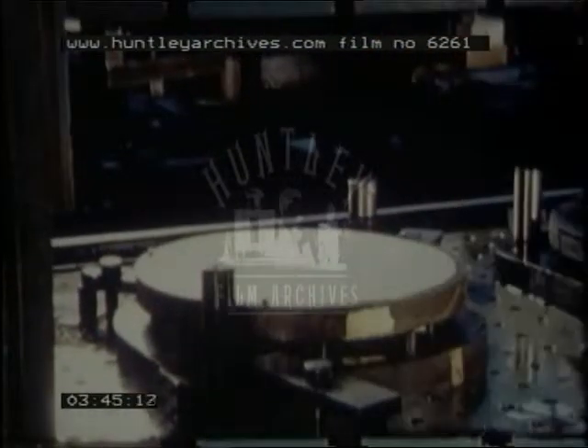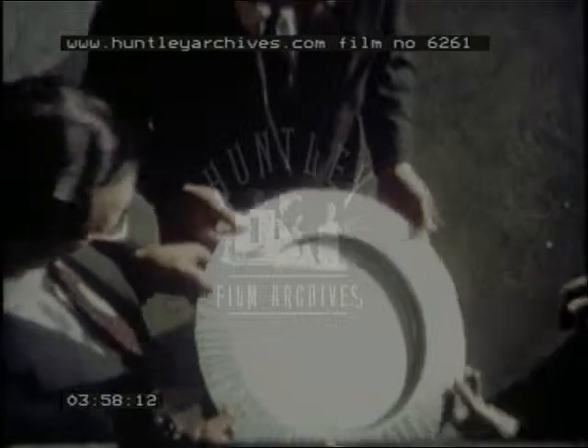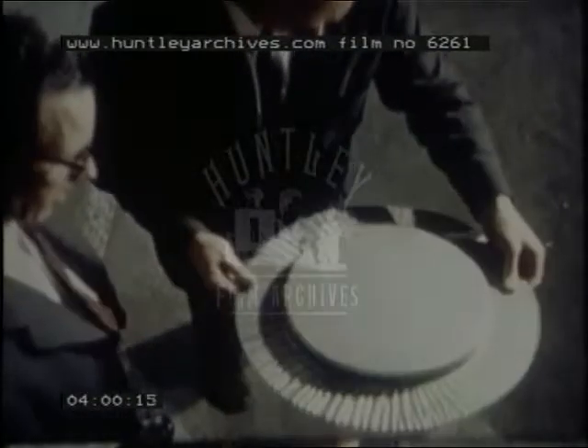Staybrite stainless steels, although extremely ductile, are also very tough. In press work, therefore, high holding down pressures are required. Otherwise, this occurs. In the case of a single-action mechanical press, greater restraint is put on the blank by increasing the pressure on the air cushion.